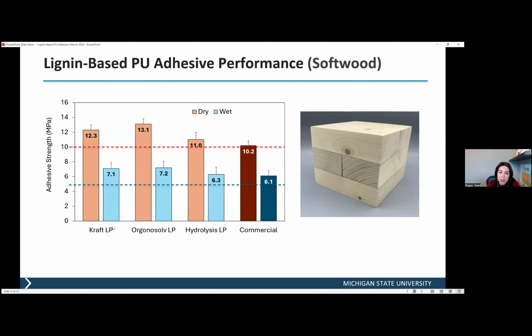When we look at this data, the ones on the left are dry adhesion tests, and the blue ones are the wet adhesion tests. The first one is the lignin-based adhesive we made with the kraft softwood lignin. And then the middle one is with the organosolv wheat straw lignin. And then the last one is the hydrolysis hardwood lignin-based adhesive. And the final one is the commercial one-component polyurethane adhesive.